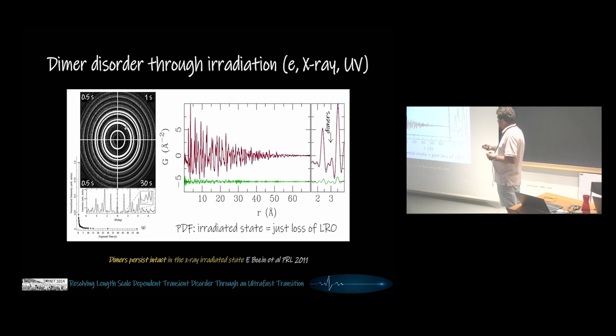These are 4 different diffraction patterns from an image plate that correspond to different exposures. The detail is that one multiplet of Bragg peaks, because this is a low-resolution measurement, disappears. It has this kind of time dependence. The time scale here is in seconds. So you can melt the long-range order, but if you take a look at the PDF originating from the same data, you do see that the dimers are staying put. So you're not destroying the dimers, you are essentially just destroying the long-range order.